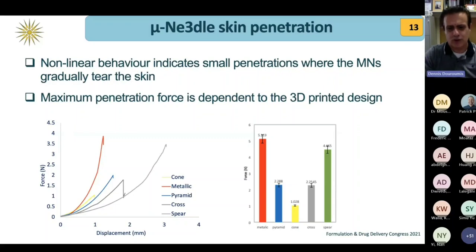What we did, of course, we evaluate the piercing capacity of these polymeric microneedles, and we found that the shape of the microneedle is very important. Depending on the shape, we can apply different forces to pierce the skin. This was quite critical, and we found that the piercing forces are less compared to metallic microneedles.